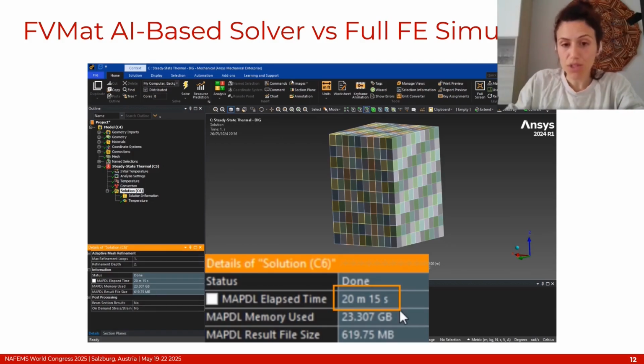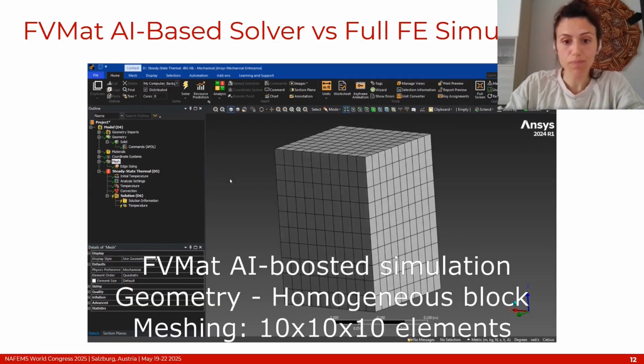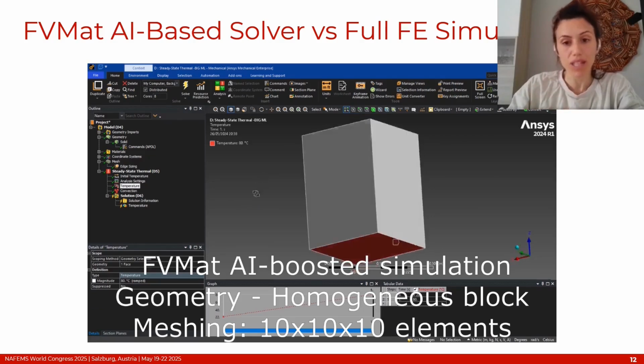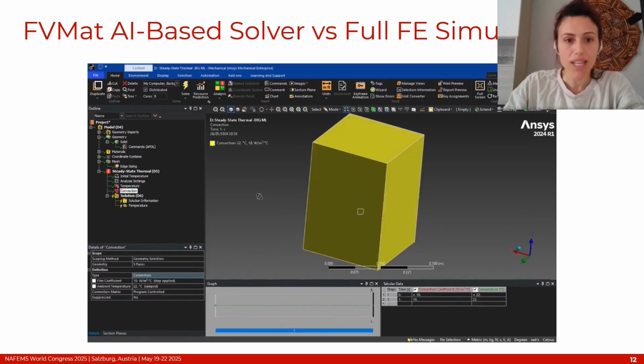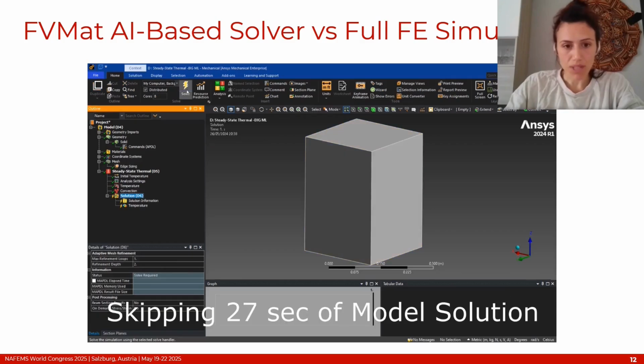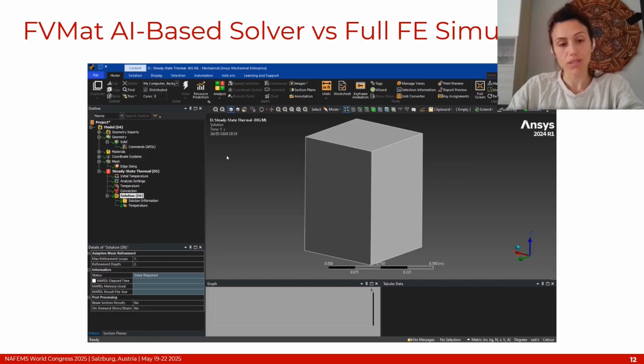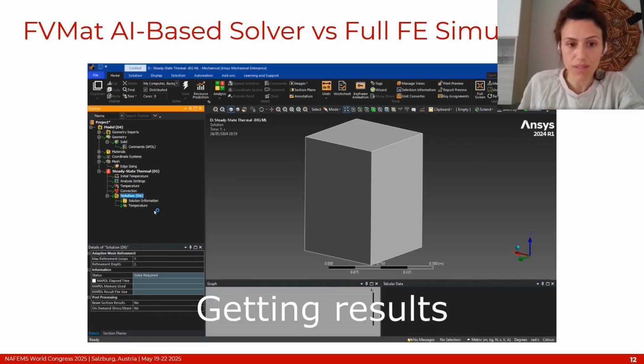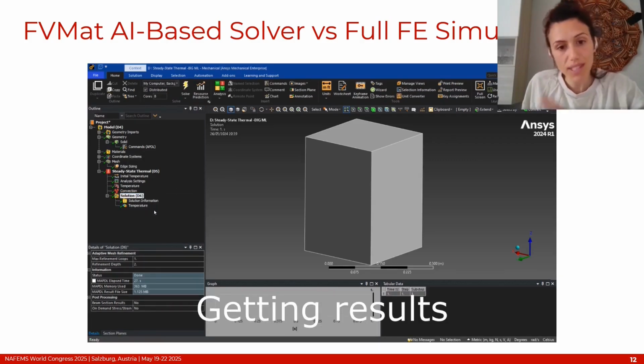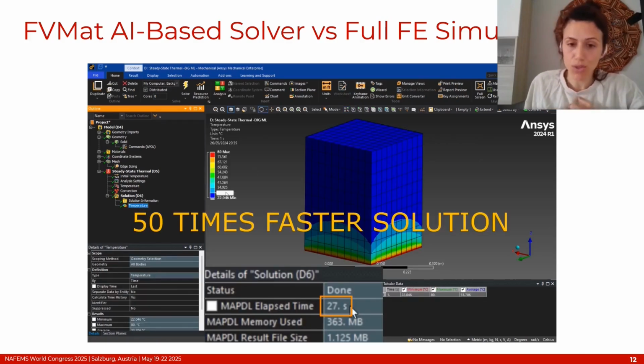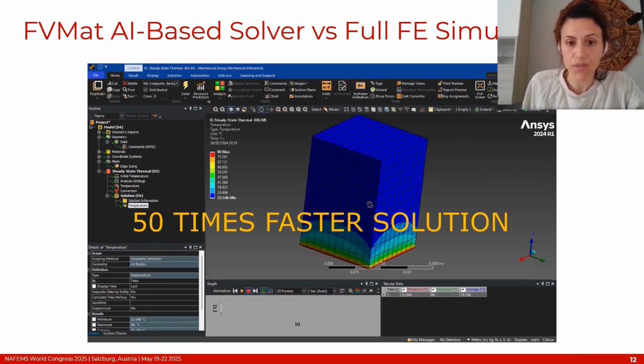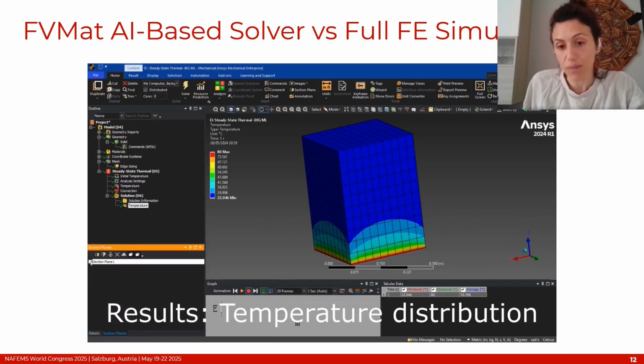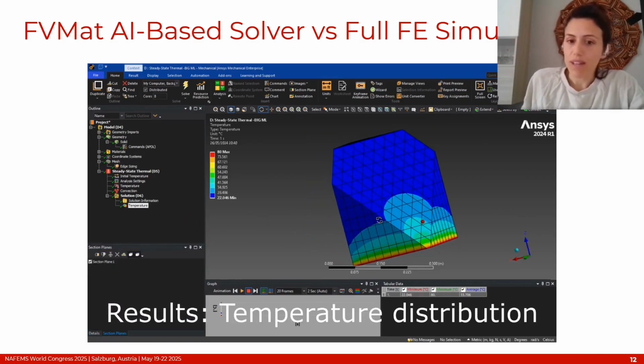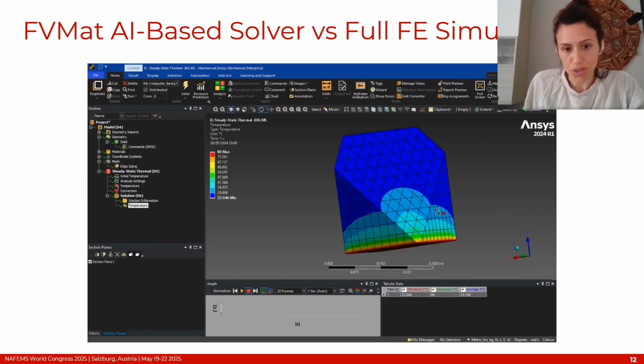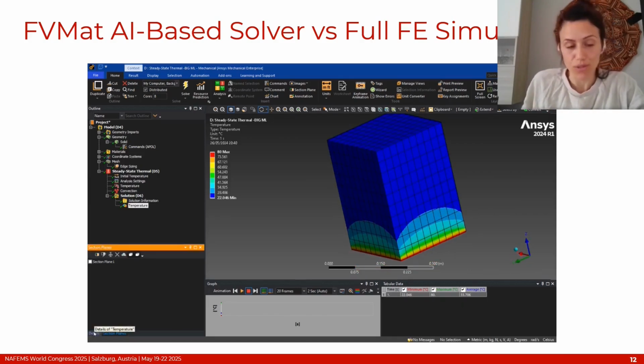Here I show the same simulation with our AI-based tool, with the same geometry. So I have 10 by 10 by 10 unit cells. The simulation starts with the same boundary conditions, and it just takes 27 seconds to get the solution. We get the results, and the temperature profile after 27 seconds is very similar to what we've seen in the full detailed finite element simulation, with a much reduced computational time, by orders of magnitude.